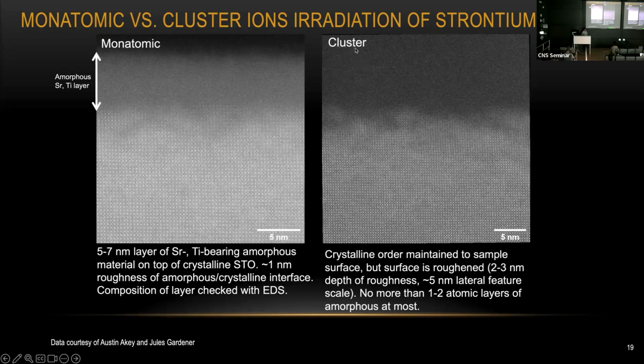You can see these two images are the STEM images, and we can see the crystallinity, each atom, nicely. But for the piece of sample using monatomic etching, right on top here, you can see a layer of amorphous titanium and strontium. But for the one with the cluster source etching, that's just a clean surface right on top. So it shows that when we do the monatomic etching, we really do a lot of damage on the surface. So if you really care about the very top monolayer, 1 angstrom, 2 angstrom, then the cluster source etching might be a better candidate for you.